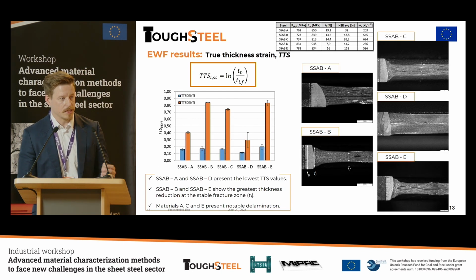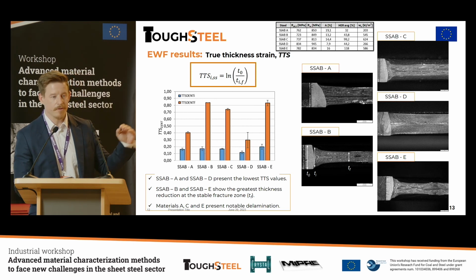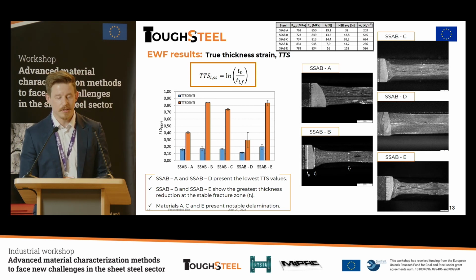Then more results on these essential work of fracture tests. Here we have also results for the true thickness strains. And what we can see here, again, is 2 different levels of results. These are aligning really well with the essential work of fracture results, that the 3 high-level materials with the fracture toughness are also showing really high true thickness strains in these specimens.